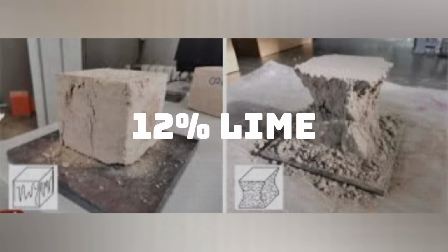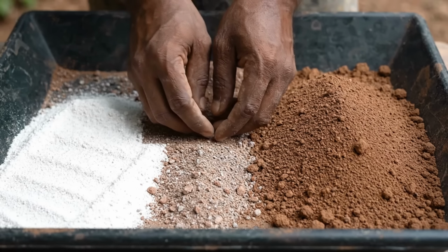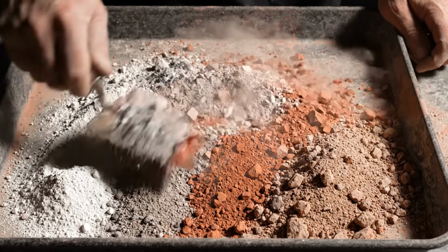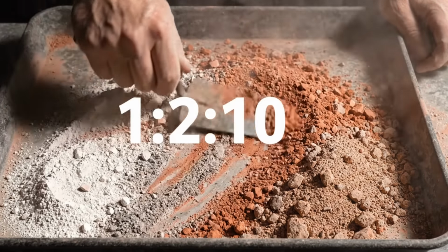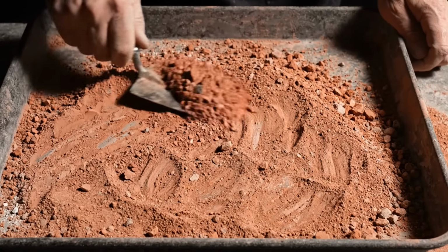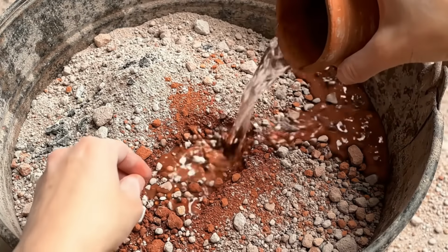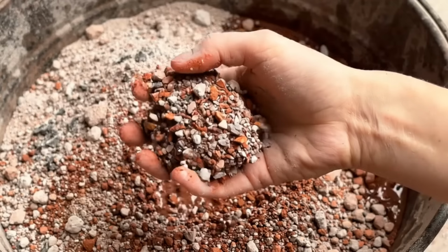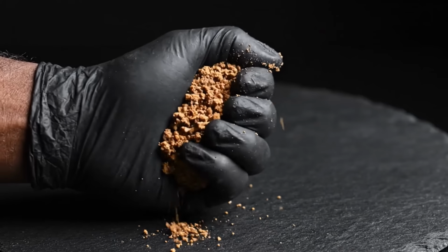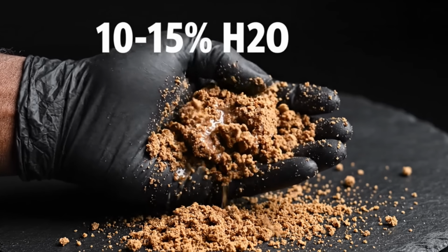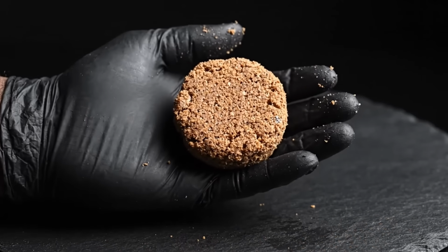A 2022 University of Granada mechanical study by Avila, Puertas, and Gallego identified 12% lime by weight as the optimum for compressive strength in lime-stabilized rammed earth. By volume, roughly 1 part hydrated lime, 1 to 2 parts ash or brick dust, and 7 to 10 parts subsoil. Mix the dry ingredients thoroughly first. Add water gradually until you reach roughly 10 to 15% moisture by weight. The mixture should look like damp, coarse breadcrumbs, clumping tightly when squeezed, but not sticking to your skin.